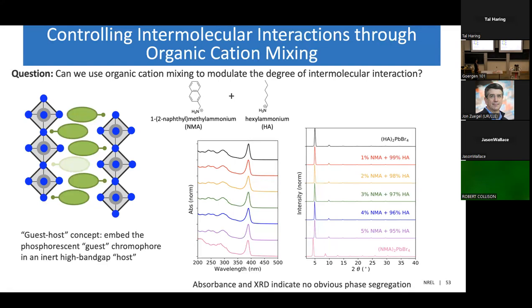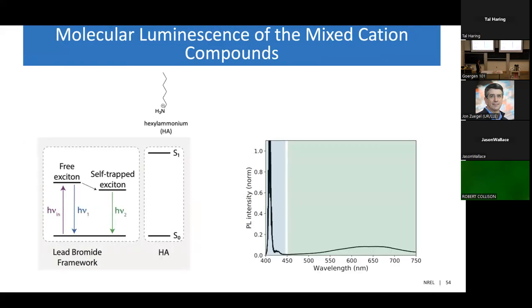And I made a series of these perovskites, and the point of this absorbance and thin film XRD are just to show that there's no obvious phase segregation, which would show up as peak splitting in the absorbance and XRD peaks. So now let's take a look at the photoluminescence from these compounds in turn.